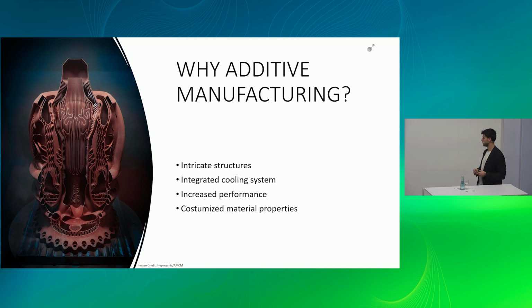That increases performance a lot, and in additive manufacturing we can customize material properties. For these engines, that mostly means to adapt the surface roughness. If you have higher surface roughness, you have higher pressure drop in the cooling channels, which could be bad, but on the other side you also have enhanced thermal performance due to that increased surface roughness. What basically happens is that higher surface roughness creates microturbulence. These microturbulences lower the pressure, so you have a pressure drop. But on the other side, these turbulences also increase heat transfer. So it's a bit of a trade-off which surface roughness you actually want. Not necessarily the lowest surface roughness is also best for the application.